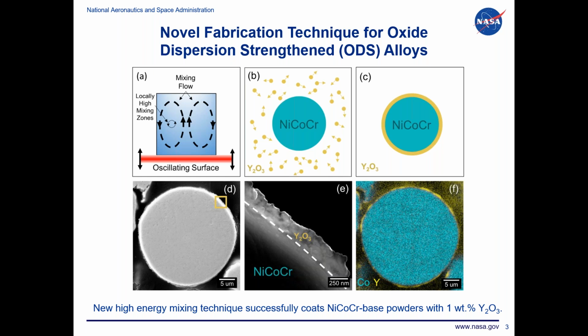Initially, we had started with ball milling and more conventional ways to produce ODS powder, but all of those are still very expensive, and they led to a lot of issues in terms of printability. Ball milling heavily deforms your metal powder, and it adds a lot of defects when you try to print it. What we found is that you could coat metal powder. In our case, we use a high energy mixing technique called a resonant acoustic mixer. We could coat the metal powder with nanoscale oxides.